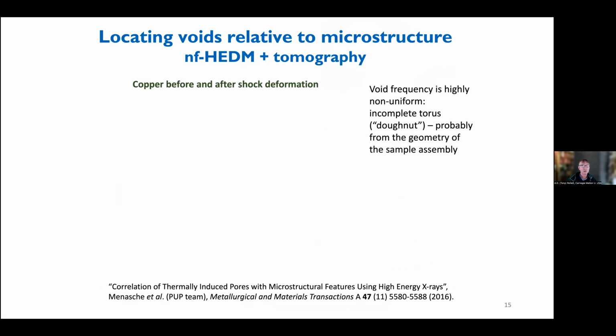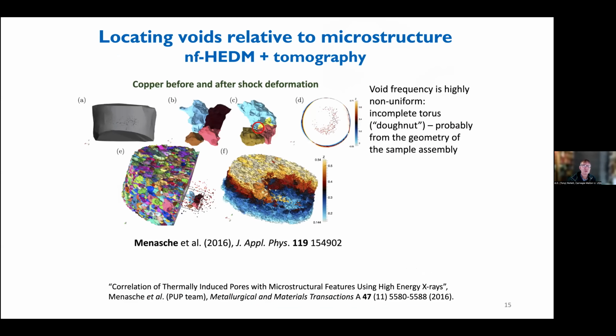Okay, so what we did with this was to, from the initial experiment, which allowed us to map the entire microstructure, so that's this colored picture here with a cutaway, and then take the recovered piece. And it turned out that the main point of the recovered piece was to do computed tomography so that we could locate all of the voids. The shock trapping wasn't perfect. The incipient spallation, the voiding, occurred in a curious sort of donut shape. But nevertheless, there were plenty of voids there, several hundred of them.